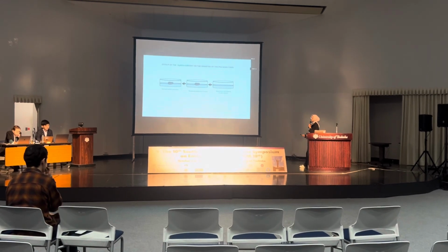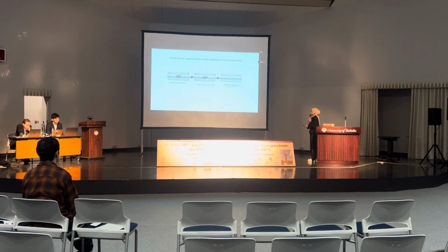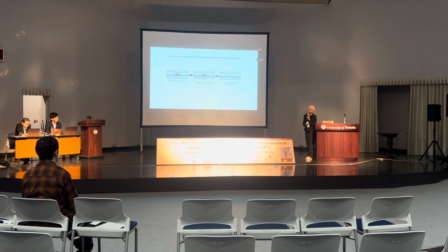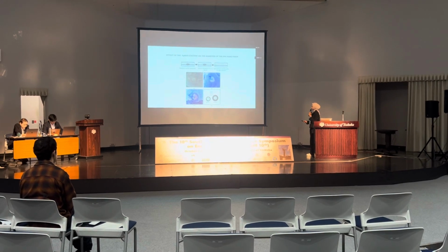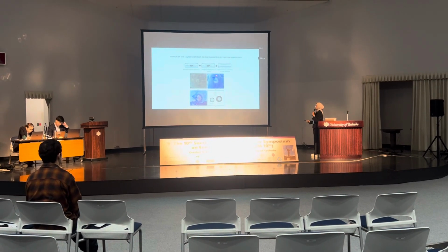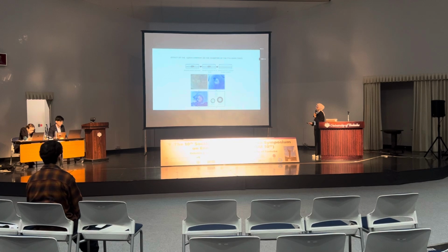Finally, we expand this research by investigating the bacterial activity using the clean zone method. In this method, the E. coli bacteria was spread on the agar and the sample was put on it and incubated for 24 hours. Finally, I found that more silver nitrate is more effective in blocking the growth of the bacteria.